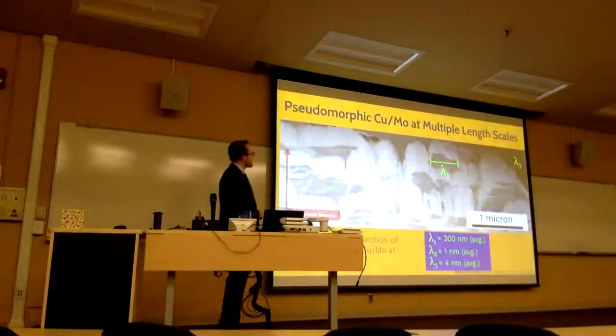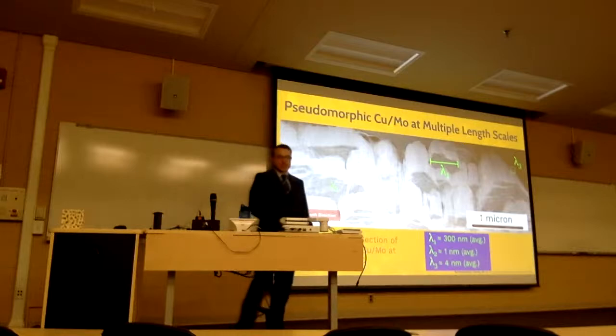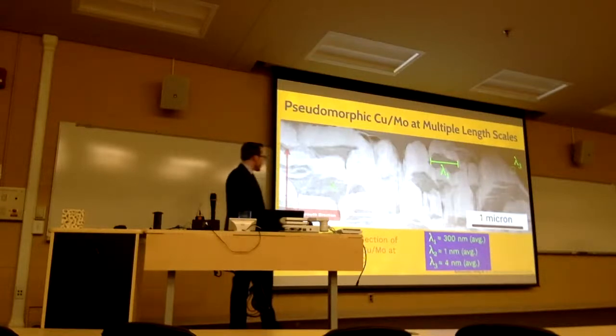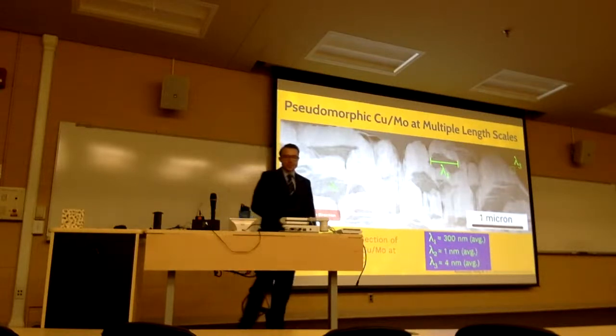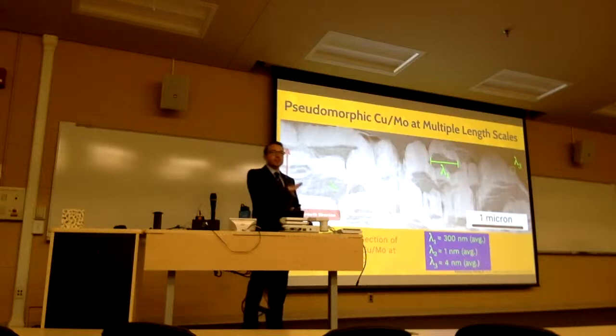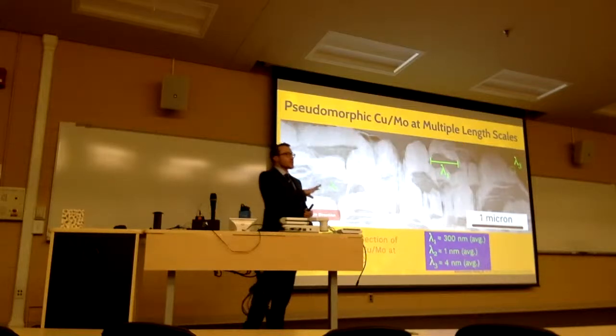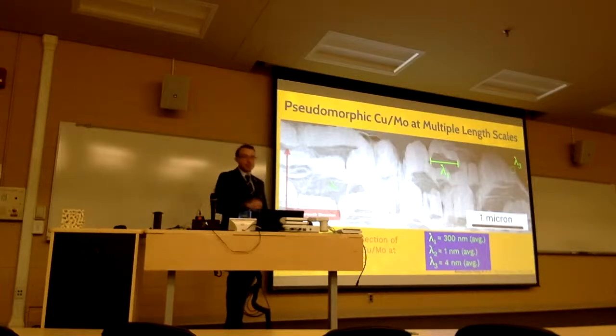So at the lowest deposition rate we experimented, here is a high-level view of that sample in cross-section. At the sample deposited at 400 degrees C. And what I'd like to point out to you here is before we could describe those phase-separated like morphologies with 1 length scale. Here, we can no longer do that. We have to describe them with at least 3.